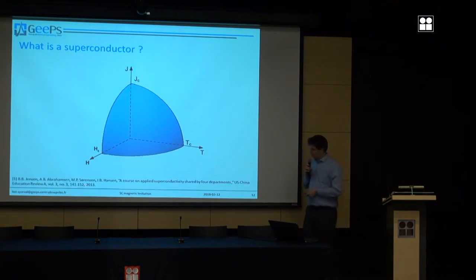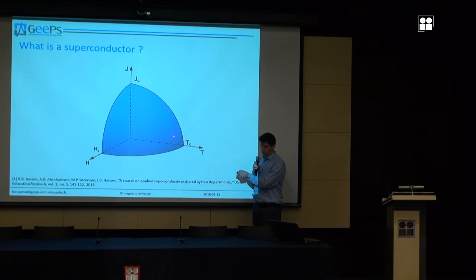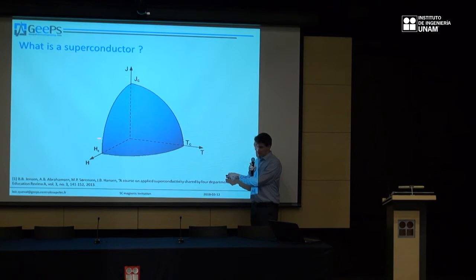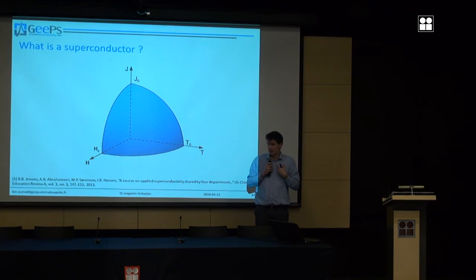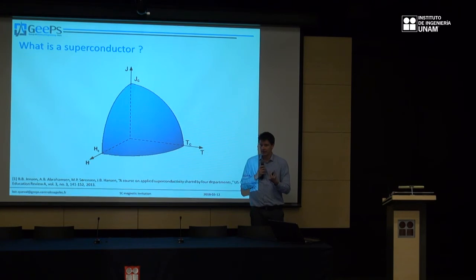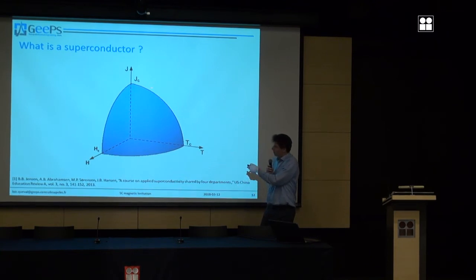As I told you, if you want to be a superconductor, you have to be under a given temperature, you have to cool it down, and you have to be under a given field. And actually the field depends on the applied external field, and on the field created by the material itself. It's a superconductor, so you can have a superconducting current. This current is creating a field. So the current inside the material and the field are related. So if you want to be a superconductor, you have to be under these three numbers: critical temperature, TC, critical field, HC, and critical current density, JC.